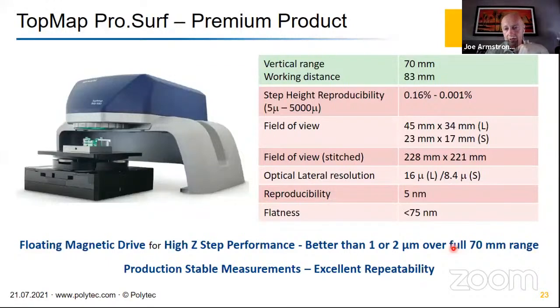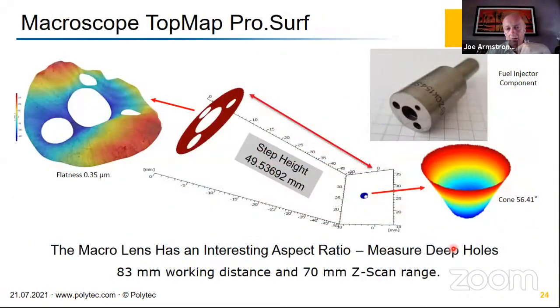Just a quick, because I'm running out of time, a quick introduction on the macro lens system. This has a floating magnetic drive. So the capability of measuring large steps is just incredible. If you measured a 50mm step, your measurement uncertainty would be good to 1 or 2 microns. It is really an excellent product for large step height measurements. Pretty unique. And with the macro lenses, you can measure the flatness.